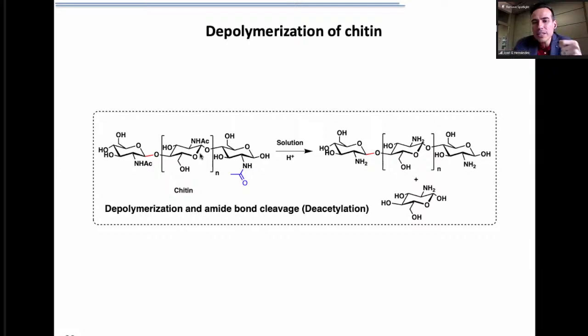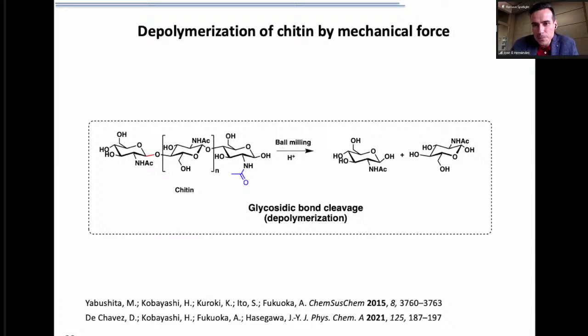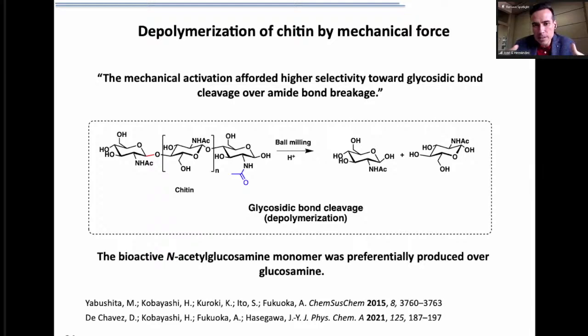When people try to do this reaction mechanochemically, so they put it in the ball mill, they observe a different type of selectivity in the reaction. There was only cleavage of the backbone of chitin, so there was no deacetylation. So somehow the mechanical activation that is happening during the ball milling procedure is favoring the reaction and is achieving higher selectivity towards the glycosidic bond cleavage over the amide bond breakage. And the question is why?